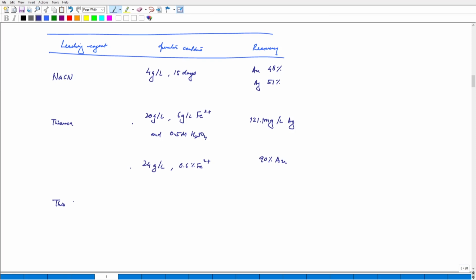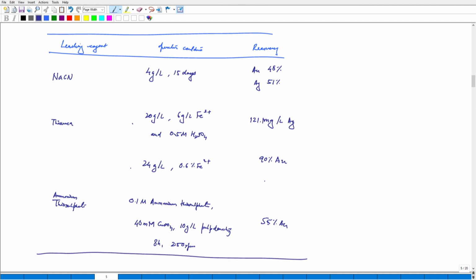Finally, thiosulfate. So in this case it is ammonium thiosulfate. So if this is the case, then we have 0.1 molar ammonium thiosulfate. In this case, we are going to use 40 millimoles of CuSO4, 10 grams per liter pulp density, which is basically S/L, and in this case we need 8 hours, and they've mentioned RPM also, so 250 RPM, and this gives us 55% gold. Mentioning some of the references we have.